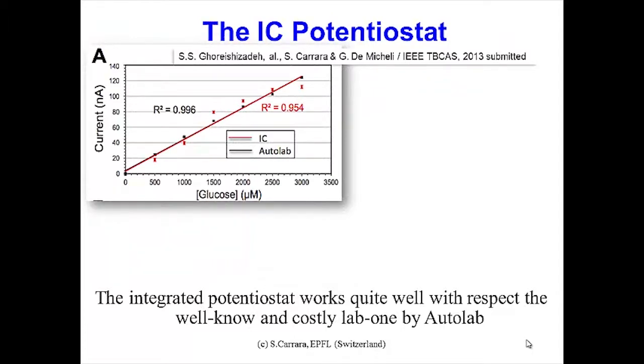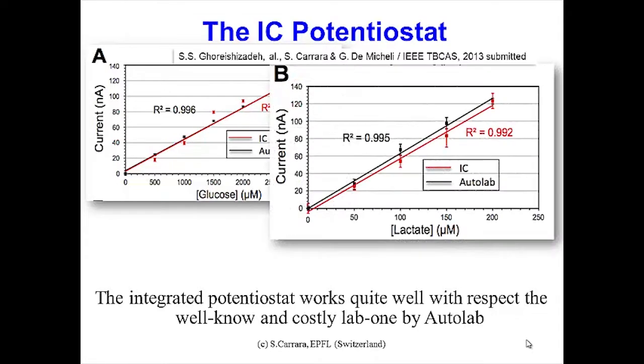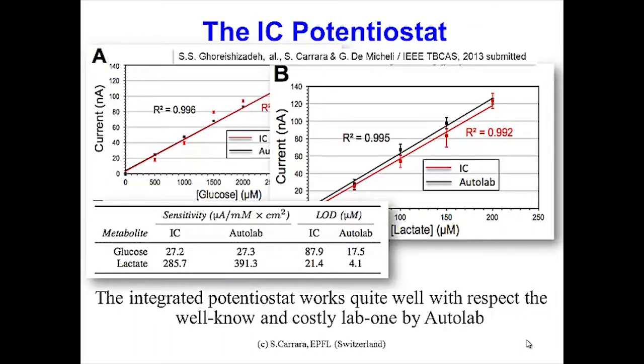And these are some tests we have done comparing the typical lab equipment, which costs $40,000, with our integrated chip, which is 1 millimeter by 1 millimeter. As you can see, we get a quite good correlation between the 2 measurements. We did it for glucose, and also for lactate. In both cases, these are chronoamperometric measurements, fixed potential, measuring only a current that varies with the concentration.